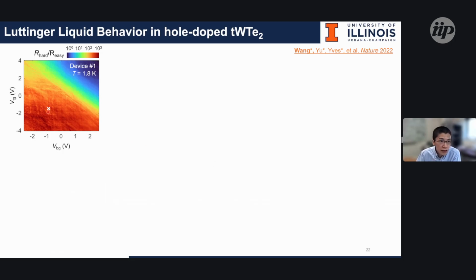So we park the gate, meaning we fix the condition as well as the displacement field into one confined condition. We try to maintain the displacement field at 0. So here we park the gating or doping density of the sample, and then we measure the transport property across the wire.